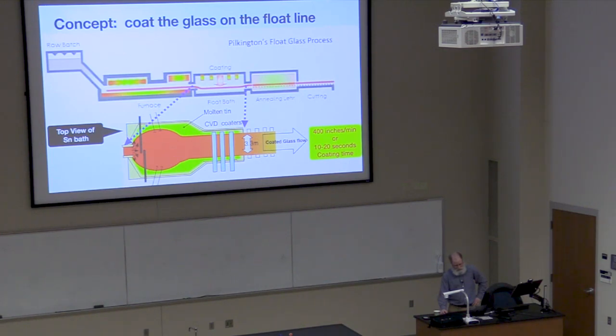By the time it gets here, you can see how the bath now narrows down. By the time it's here, it's stable in thickness. It's not going to get any wider or any thicker. But it's still too hot to lift out onto these rollers. So the original purpose of this part of the bath was just to get that formed sheet into a temperature where you could handle it. So that's when the glass scientists of the 80s said, why don't we try to coat it right there? It's flat, it's hot.